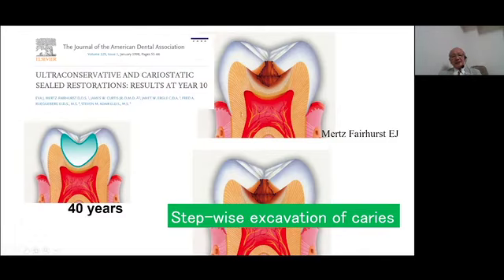Of course, in the United States, Dr. Fairhurst reported an excellent paper regarding the sealed restoration technique. Sealed restoration technique is to intentionally leave the caries infected dentin, and the cavity is sealed by the adhesive restoration. Even after 10 years, the clinical cases showed a very good performance. No pulpal irritation or extended caries region. So that's why good sealing of the cavity is very important even when we leave some infected caries regions.